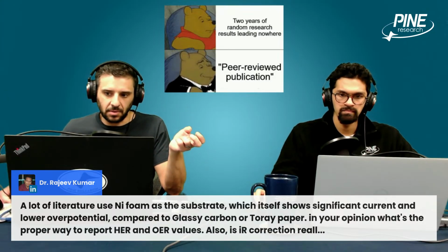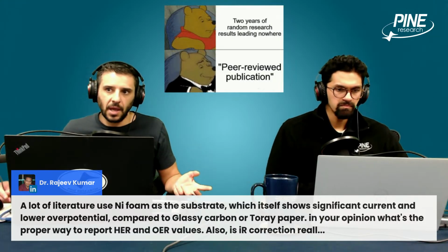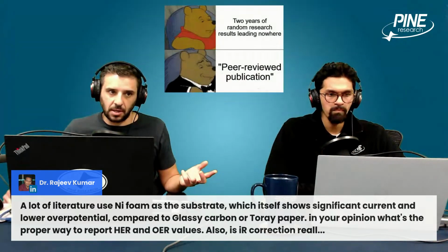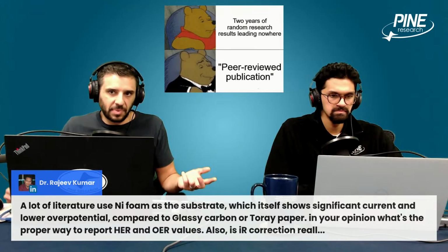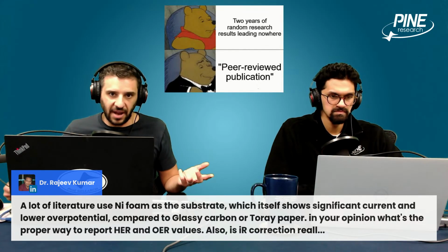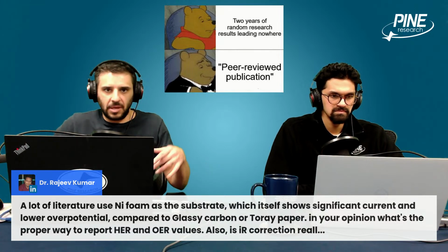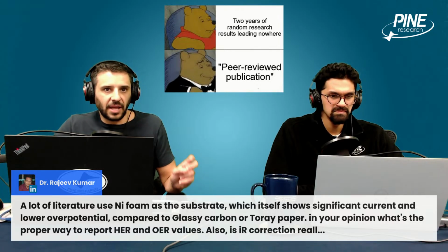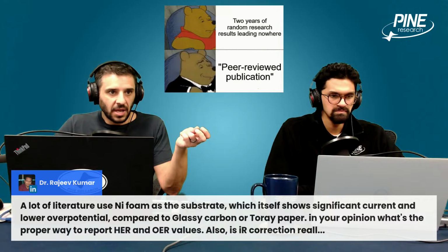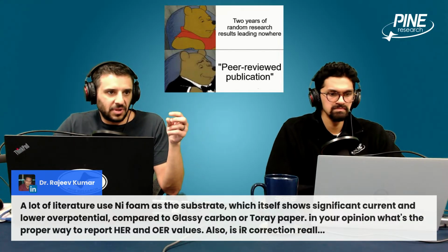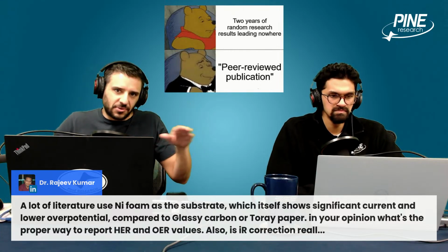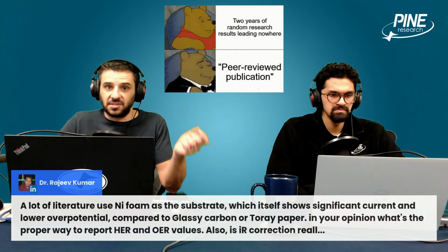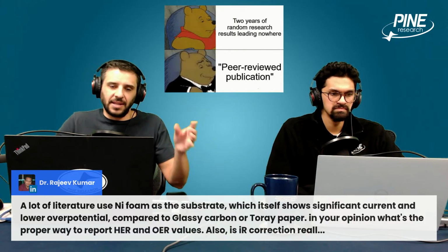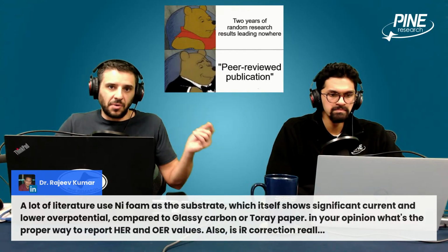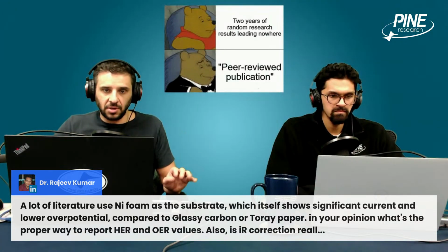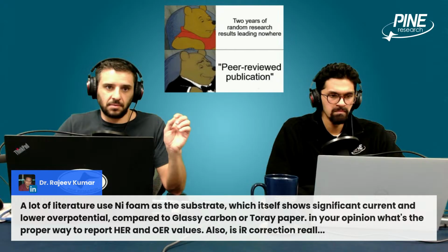This is also one of the things about carbon, right? I mean, you can put platinum on carbon and do OER and HER, and nobody subtracts the carbon baseline, because it's mostly irrelevant, right? Its overpotential is like hundreds of millivolts worse for every reaction. But you could make the argument, if you wanted to be a purist in some sense, that even with platinum on carbon, at some overpotential your current is whatever, you could subtract a couple of femtoamps from that, to say, well, I'm subtracting the contribution from the graphite because it technically is doing some OER or HER, right? The carbon's going to contribute a little bit, but it's so negligible compared to the activity of the platinum or the palladium or whatever you're using. So that's the first answer, is that use something that